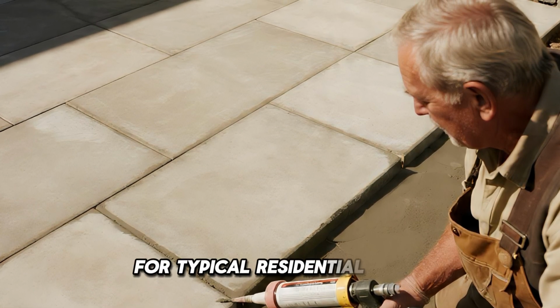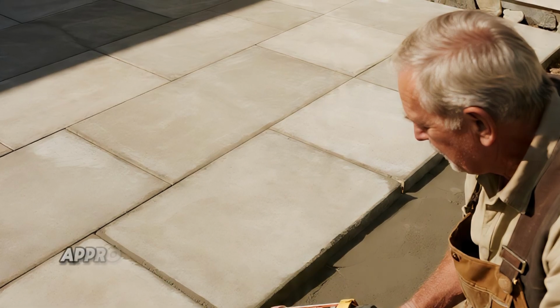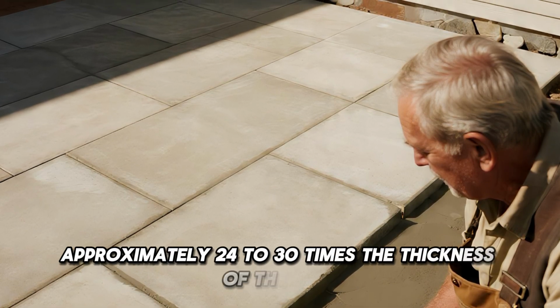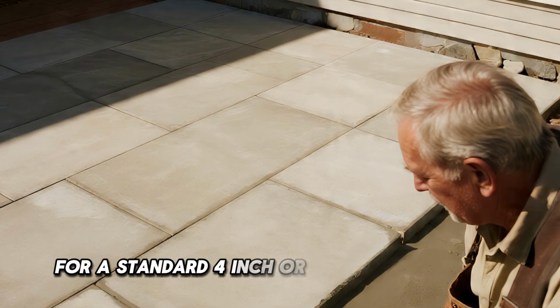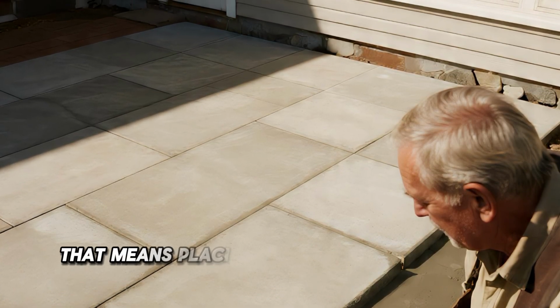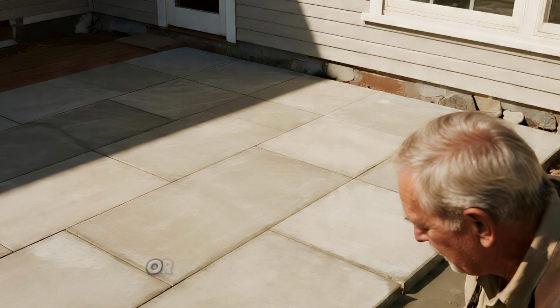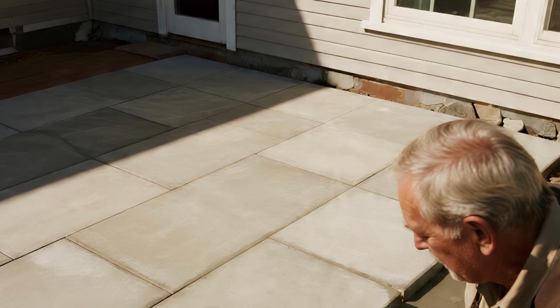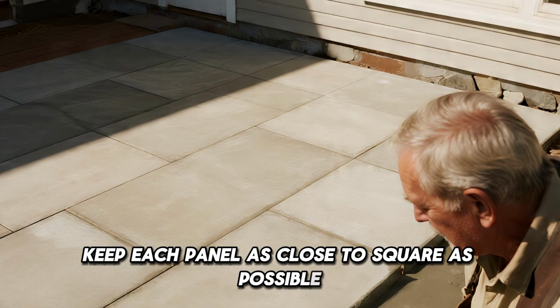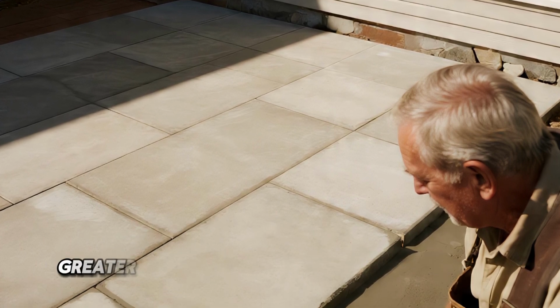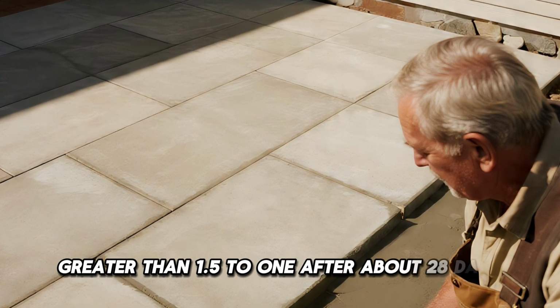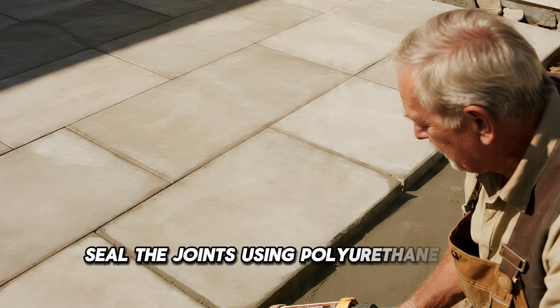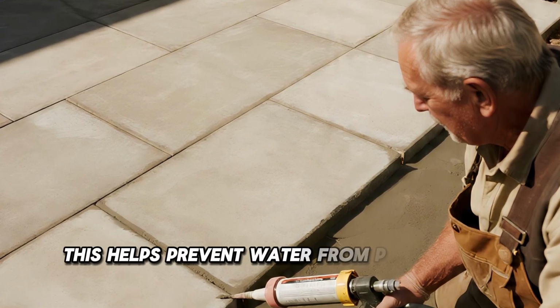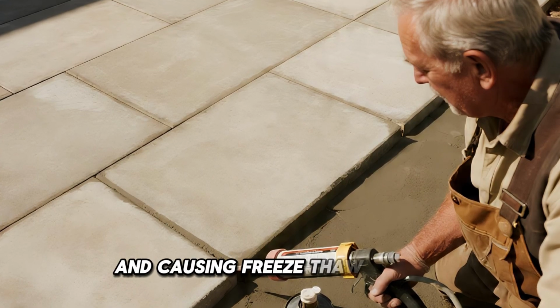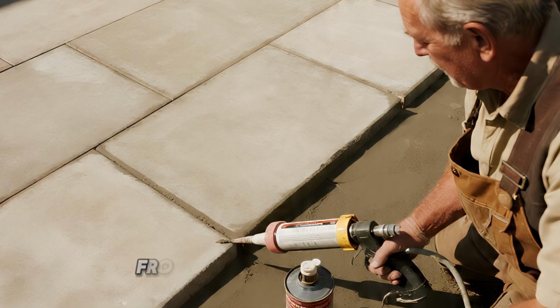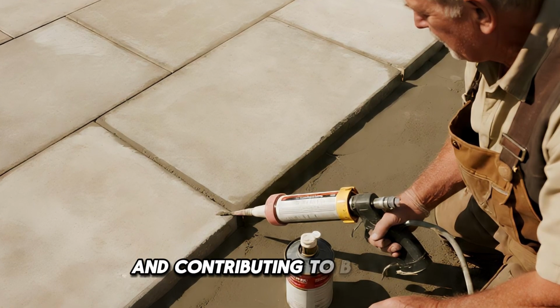For typical residential slabs, control joints should be spaced approximately 24 to 30 times the thickness of the slab. For a standard 4-inch or 100 mm slab, that means placing joints roughly every 8 to 10 feet, or about 2.4 to 3.0 meters. Keep each panel as close to square as possible, and avoid a length-to-width ratio greater than 1.5 to 1. After about 28 days, seal the joints using polyurethane or silicone. This helps prevent water from penetrating the joint and causing freeze-thaw damage, while also keeping rocks and debris from becoming packed inside and contributing to buckling.